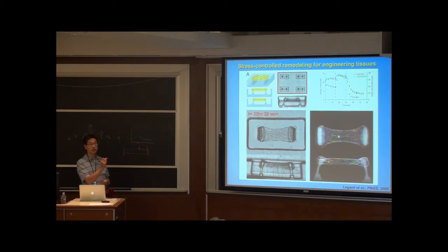cells into that gel. And as you can see, when you first seed the cells, they're distributed inside the collagen gel, and then they start to contract the gel, and you can see the gel gets pinned by these anchors, and they start to align the collagen fibers, and you can see that the pillars start to bend inwards, right? And as they bend inwards, you can back out the forces that are being generated. So we've been using this to make what I would call a little micro tissue, and studying the forces of that process.